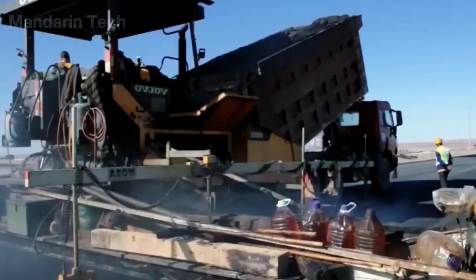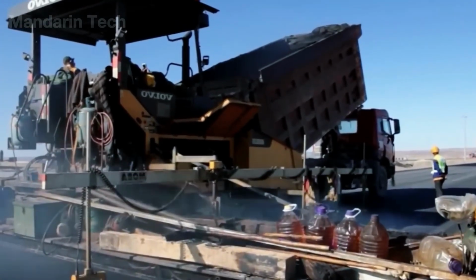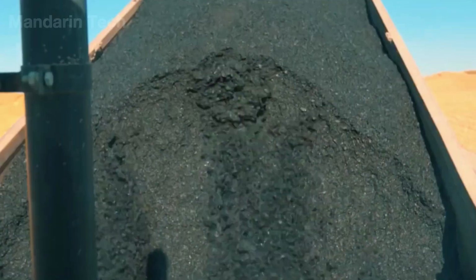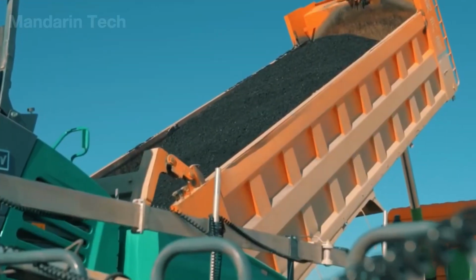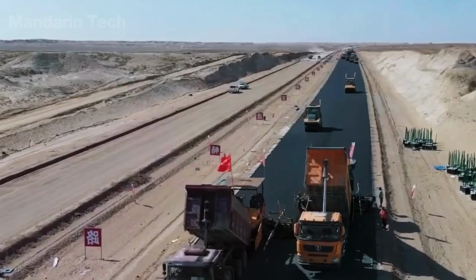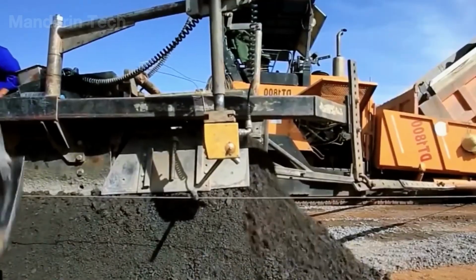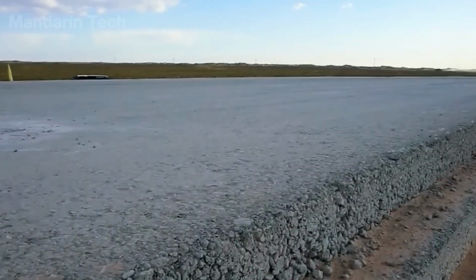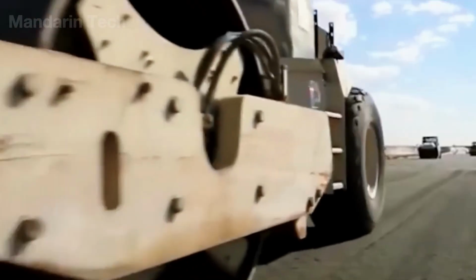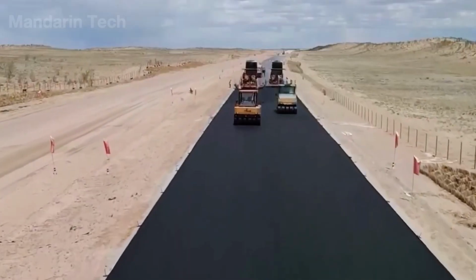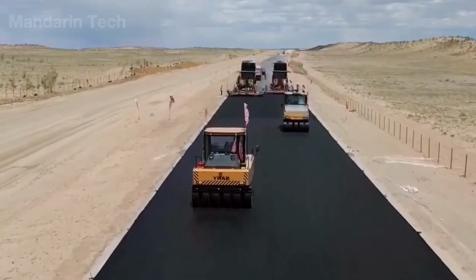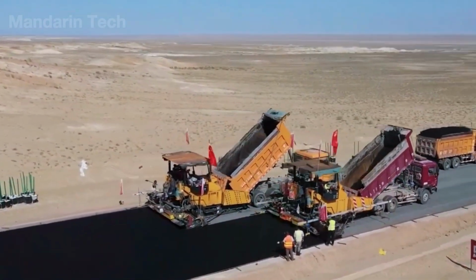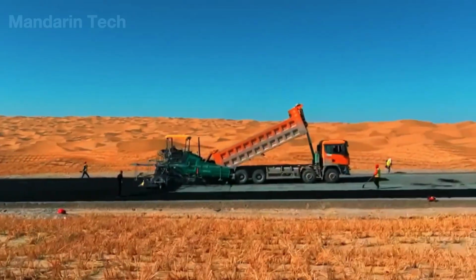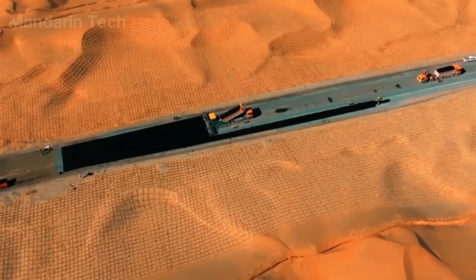At the edge of the desert, portable asphalt plants roared to life, heating stone, sand, and polymer-modified bitumen to nearly 170 degrees Celsius. From these stations, insulated tankers delivered the hot mix non-stop to the paving machines waiting on site. Each paver spread the glowing asphalt in layers about 6 centimeters thick, while steel rollers followed close behind, compacting it before it could cool. This process was repeated in a tight choreography, paver, roller, finisher, moving forward like a synchronized machine.